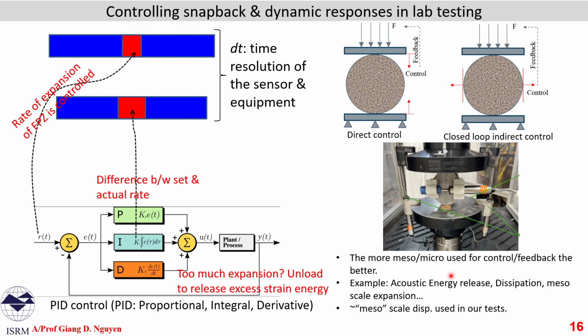Of course, this is just one example. Other examples include the use of acoustic energy release or dissipation, if we have a way to measure it, as the control. The dissipation or energy release happens mainly inside the fracture process zone at the mesoscale. So a quantity related to the mesoscale can be a good one for the control. It could be acoustic energy release, dissipation, or expansion of the fracture process zone.